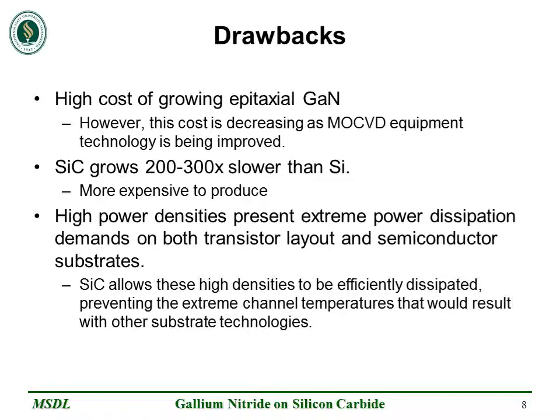There are a few drawbacks that have kept gallium nitride on silicon carbide processes from gaining more popularity. Firstly, it is very expensive to grow epitaxial gallium nitride. While improvements in MOCVD equipment technology are helping to reduce the cost, it is currently still expensive enough to be an issue. In addition, silicon carbide grows 200 to 300 times slower than silicon. This is why many gallium nitride technologies settle for silicon rather than silicon carbide.